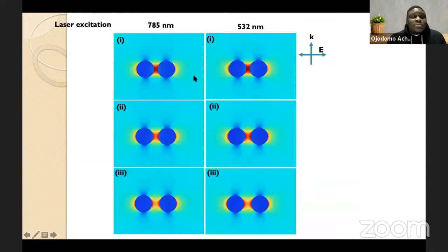Then we also simulate what happens when these materials are close together or far apart. So we have also developed a study whereby we engineered some hotspots for this SERS nanotag based on molybdenum, whereby we're able to control the distance between the two nanotags so that they can be close together. We found that if you have the closest possible spacing or nano gaps between your nanotags, which is based on molybdenum in this case, you can have more hotspots generated compared to when they are very far apart. We actually use simulation to prove the catalyzed enhancement via sandwich immunoassay protocol for molybdenum trioxide.